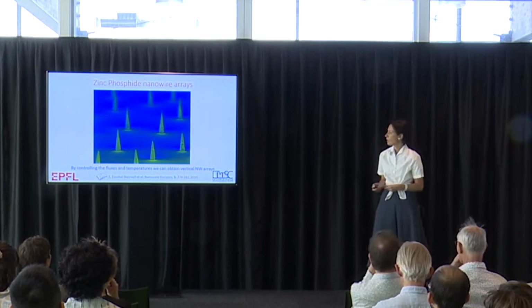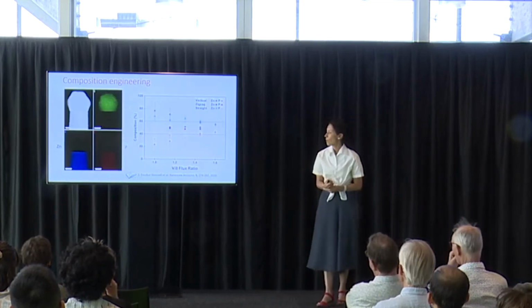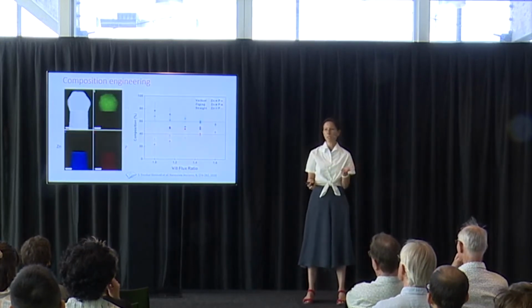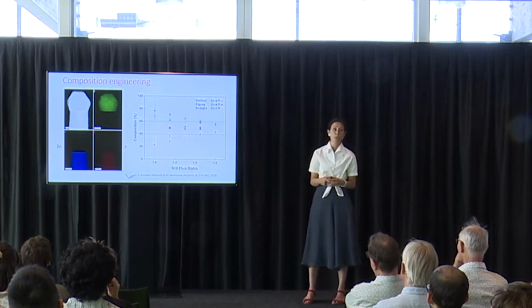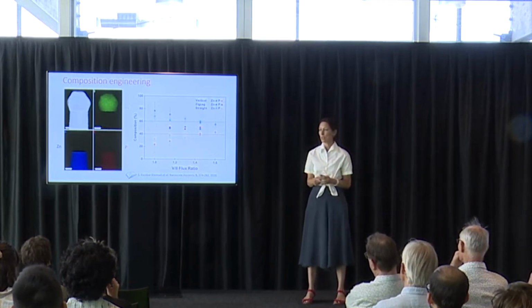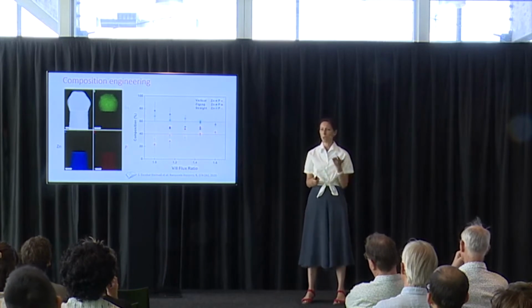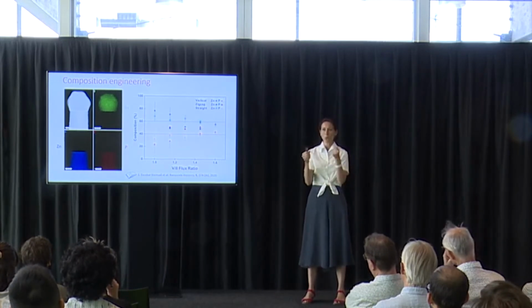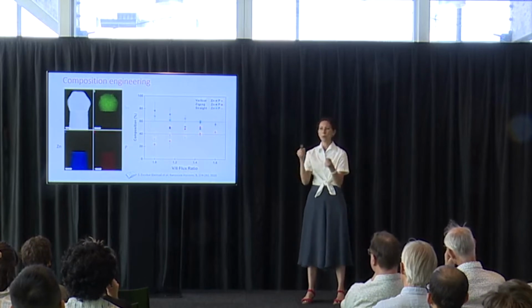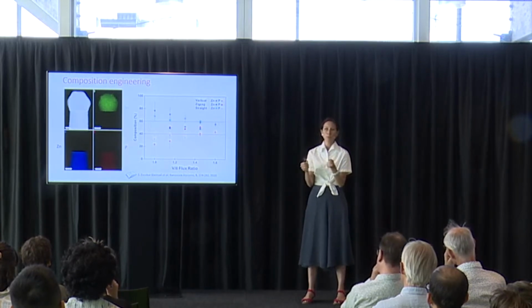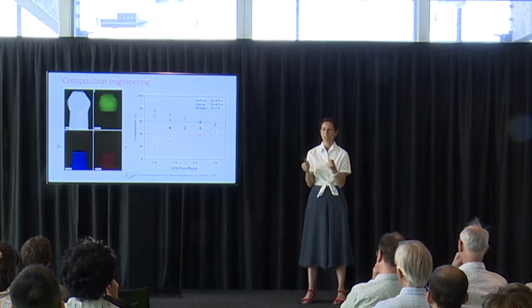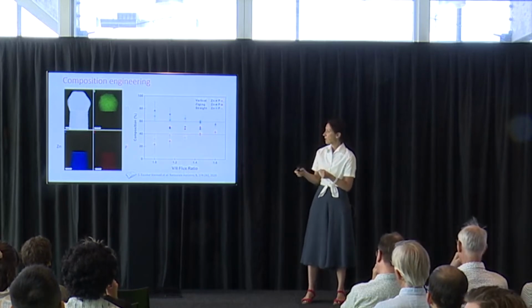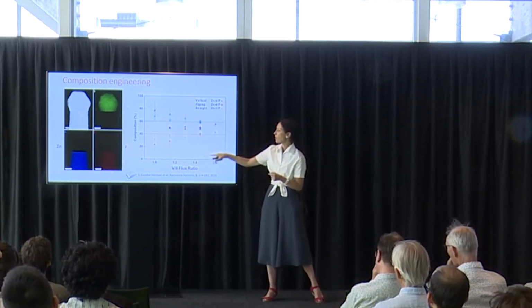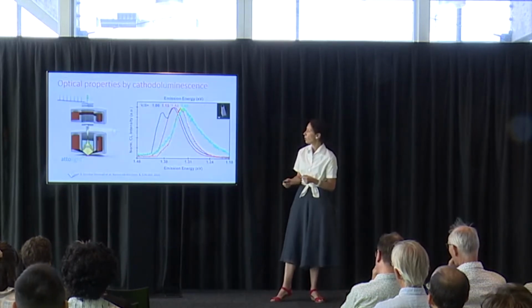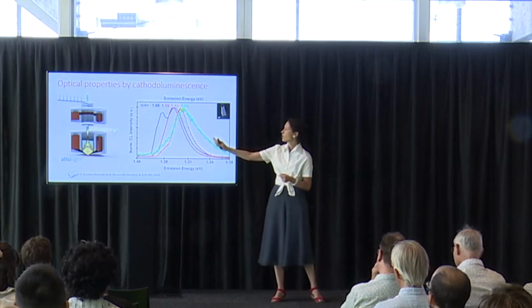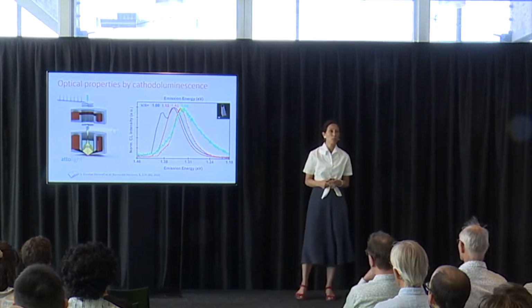What was also interesting on this is that, in fact, by changing the conditions, which means the flux of the zinc and the phosphorus, we also change the composition, which for a compound semiconductor should never happen. If you have gallium arsenide or indium phosphide, you should have 1-to-1, and if you start getting away from the 1-to-1 ratio, then your material is absolutely useless, it is scrap. But here we see we can go to compositions quite flexible depending on the fluxes, and if we then look at the luminescence, we also see that the luminescence shifts depending on the composition that we're able to change.